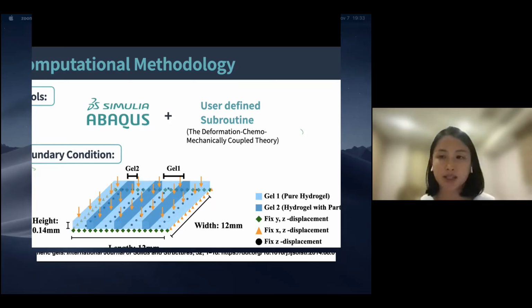So the model setting and the boundary conditions are summarized in the figure below. The size of the film is 12 millimeters wide, 12 millimeters long, and the height is 0.14 millimeters, which is quite thin. And the film consists of two parts. One is the pure hydrogel region, which we denote as gel 1. And the other is the particle cluster area, which is denoted as gel 2. Then we apply a chemical potential gradient on the top surface, which looks like the orange arrows. So it is like water flowing from the outside into the inside area.